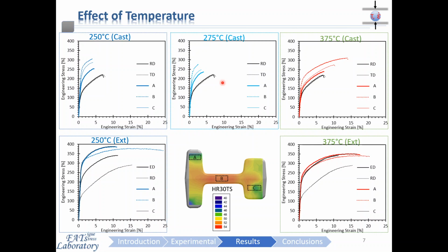So the forged materials generally are indicated by the colored lines, and the as received are the black lines. Linking that back to a previous observation, the superficial hardness correlates well with the yield strength of the material in various locations throughout the cross section of the forging. As you can see, location B generally has the highest yield strength, which is this center region that has the highest amount of strain due to forging, and it has the highest amount of superficial hardness.